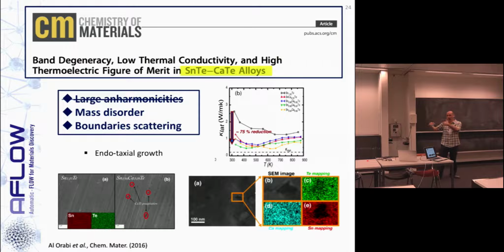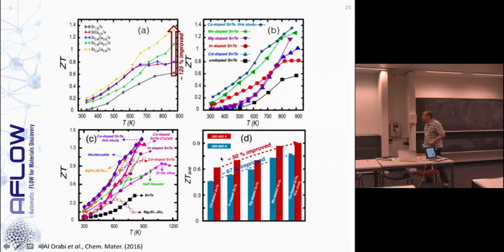This is not high throughput. This is trying to rationalize what we actually measure, right, before. So the thermal conductivity goes down by an enormous amount. So this material is actually the highest ZT material in the tin telluride family.